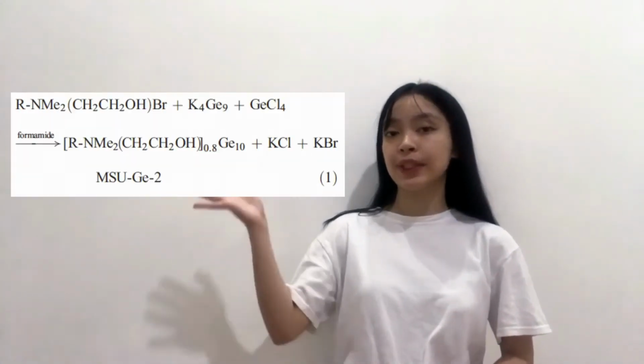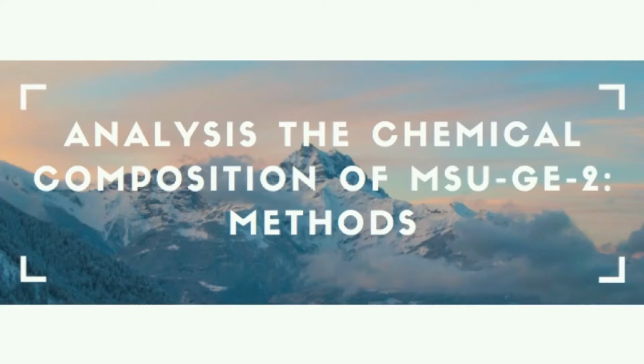Now we look at the reaction on the screen. These manuscripts were under review. The preparation of a mesoporous germanium with hexagonal pore symmetry was reported. In order to understand specifically, let's find out the origin of germanium. The material was prepared from the oxidative coupling of polymeric clusters, especially without a linking ion.